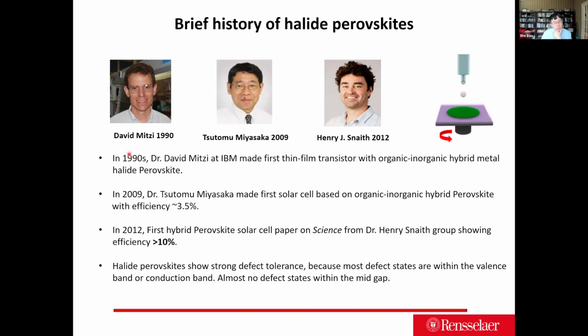Essentially, in the 1990s, David Mitzi at IBM made the first thin film with an organic-inorganic hybridized material, and Professor Tsutomu Miyasaka made the first solar cell based on the dye-sensitized structure with this organic-inorganic hybridized perovskite, with an efficiency of about 3.5%. And then in 2012, the real hero, Henry Snaith, made the first hybridized solar cell with an efficiency all the way up to 10%.